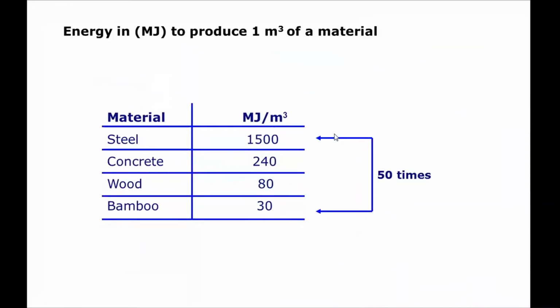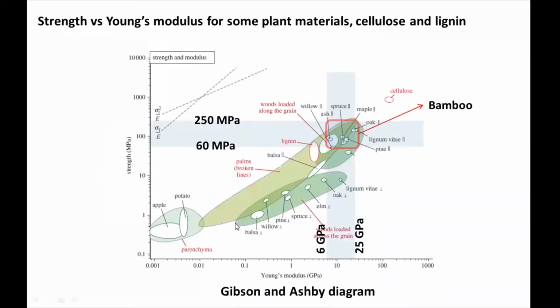In engineering, when you compare the bamboo with other materials, four important materials used for construction are steel, concrete, wood, and bamboo. Obviously, to produce 1 cubic meter of steel, you should use energy of about 1,500 megajoule, but for bamboo you can see 30, so there is a 50 times difference between producing steel and bamboo. For wood it is closer, but yet bamboo is better than wood.